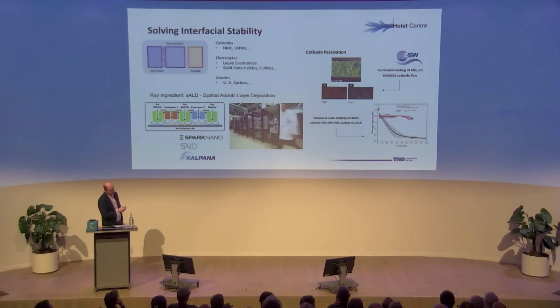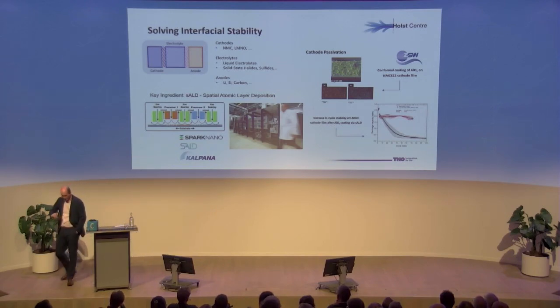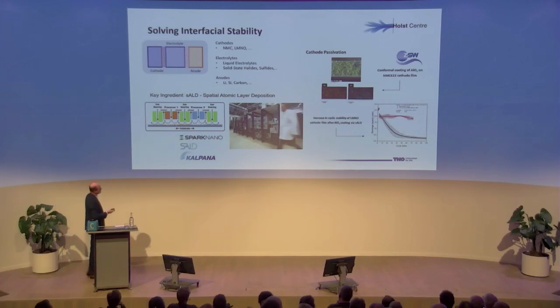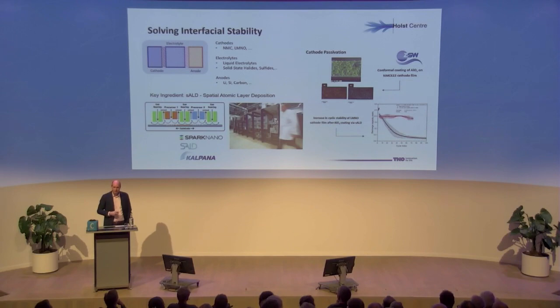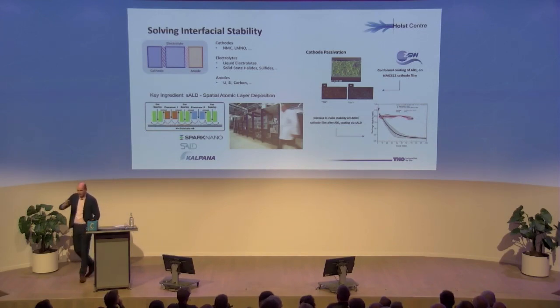We demonstrate that on a battery cathode, or an anode for that matter, but this is an example with a cathode. If you can coat over that material a very thin layer of these important materials, that you can do surface enhancement, etc., you can demonstrate that you can have the lifetime of the battery significantly improved. And this measurement is still ongoing, but what you need to see here is that normally the capacity of your battery starts fading if you start cycling. And that's the black curve.